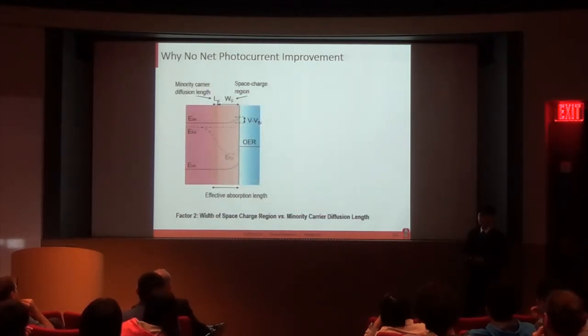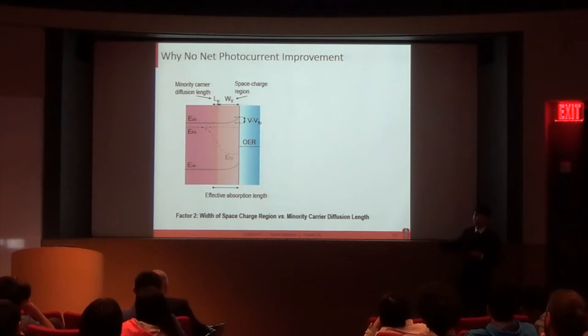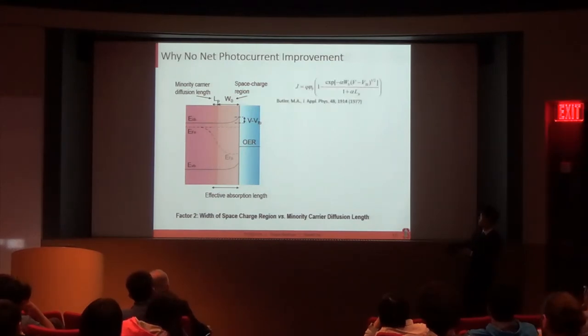And second, I also thought about the competition between the width of the space charge region and the minority carrier diffusion length. Imagine that if the minority carrier diffusion length is much smaller than the space charge region width, then even though this diffusion length increases with temperature, its net effect on the effective absorption length is very small. Such a competition has been modeled by Butler in 1977 based on semiconductor physics.